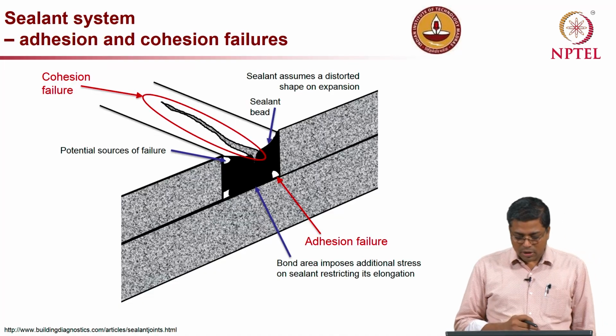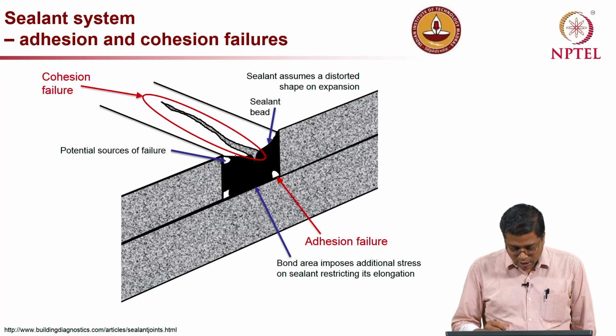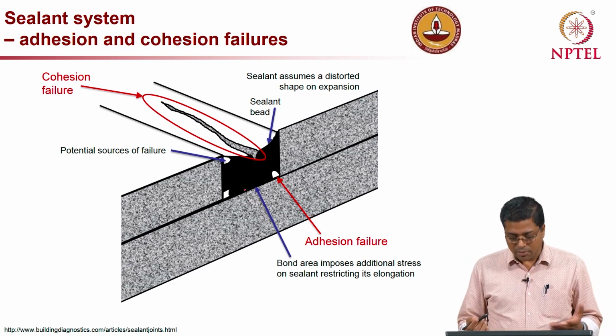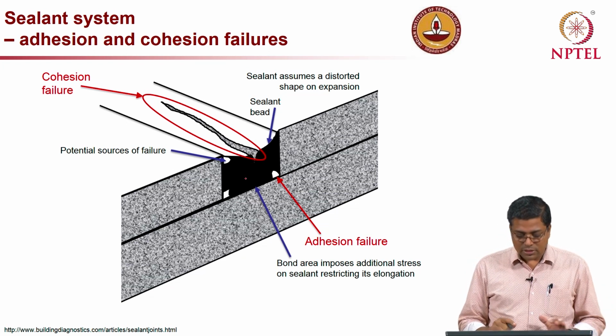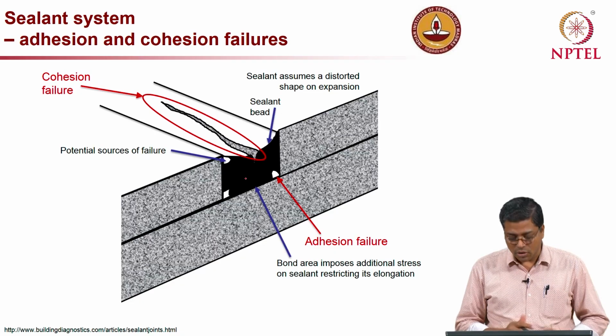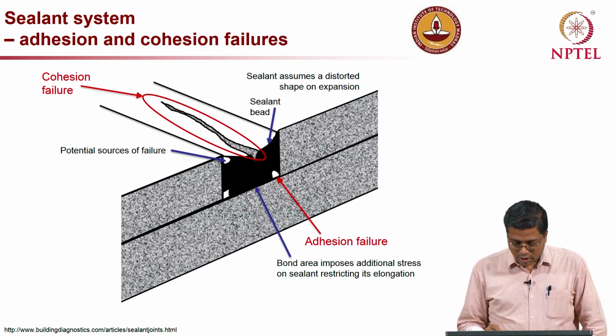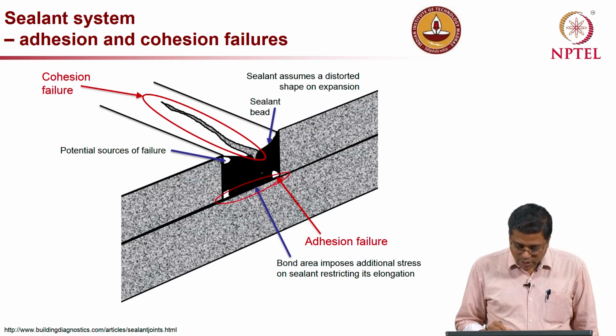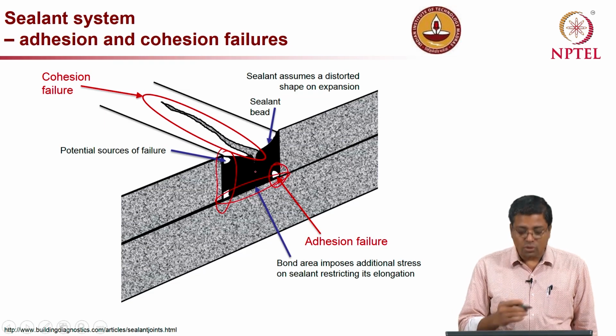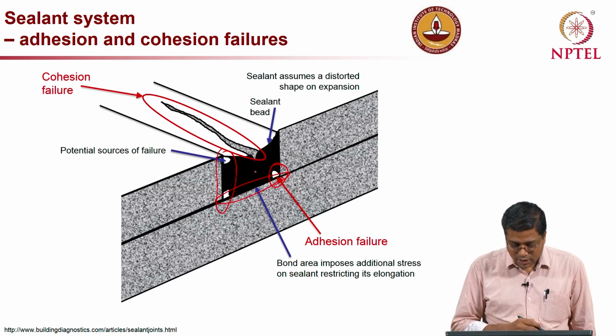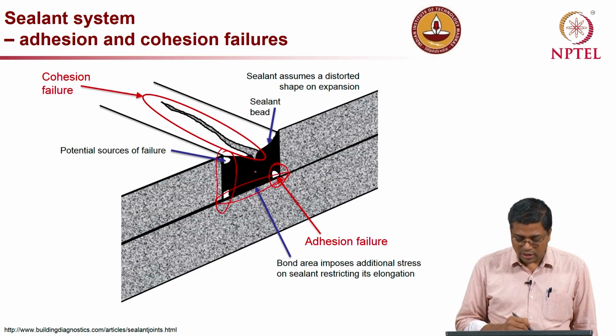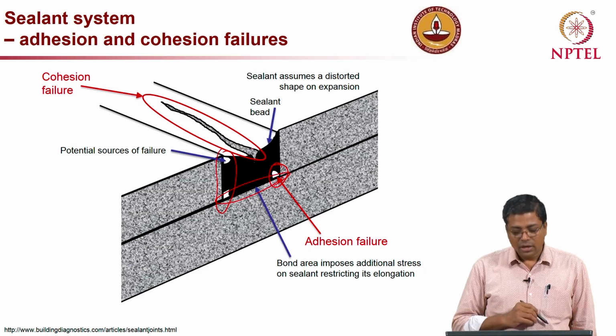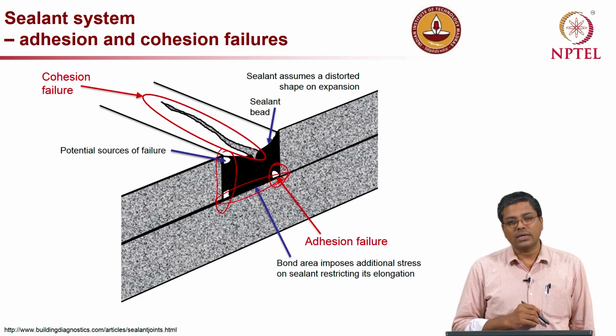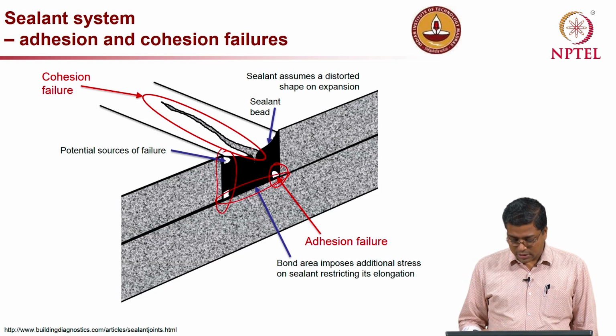Now, this is a clearer picture, just another demonstration of the same mechanism, shown here for a control joint. There is no debonding here, but anyway, you can see this is where the bond failure starts, and that too at the corners, if it is an adhesion failure. If it is a cohesion failure, then a crack will develop right at the center of the sealant.